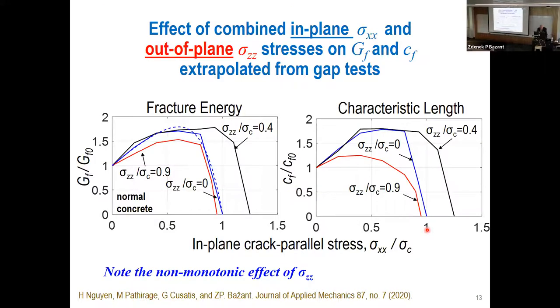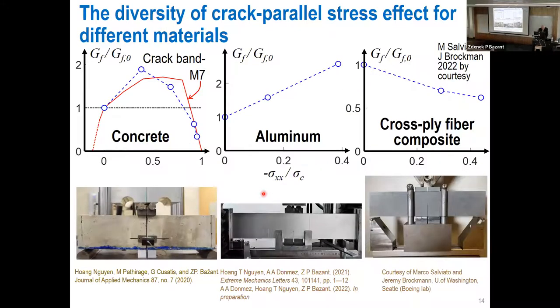Now, don't use the word T-stress because that's only for one direction, which is used in the fracture of plastic materials. I call it sigma out-of-plane stress, sigma ZZ, which also has an effect. So you change sigma ZZ to 0.4 of the strength or 0.9, you get big differences. So all these are data which cannot be captured by line crack models.